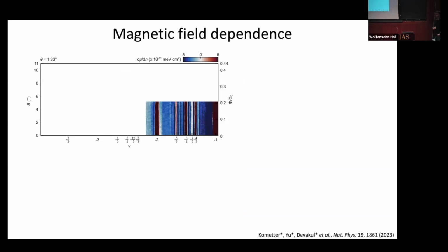Okay, so what do we see when we look locally? This is a measurement at a particular location in the sample. It has a twist angle of 1.33 degrees, which we can benchmark based on where we see different incompressible features that I'll tell you about. What I'm plotting here is inverse compressibility. On the scale, everything red corresponds to an incompressible state. That means an energy gap in the system. Everything blue corresponds to negative compressibility. That comes about because there are very, very strong electronic interactions in these systems, and that gives an overall negative background just from exchange energy, which in these transition metal chalcogenides is quite large.